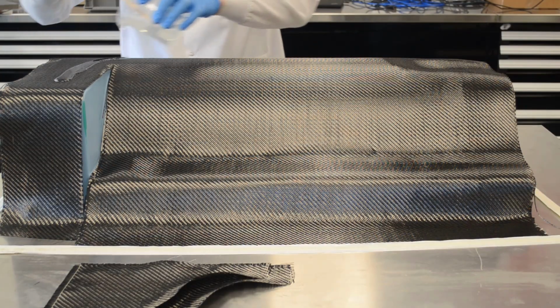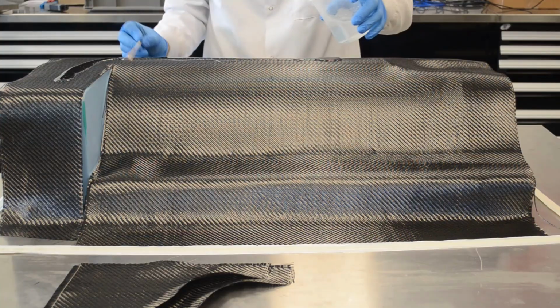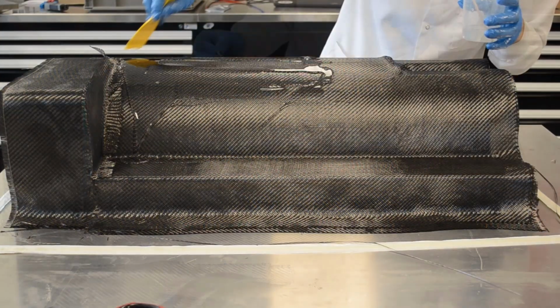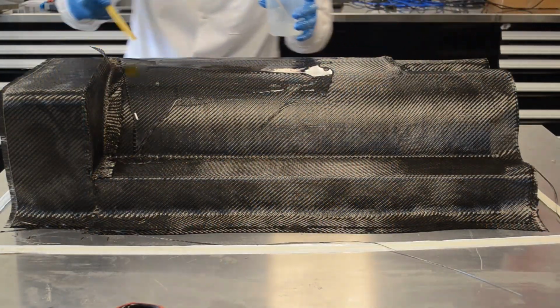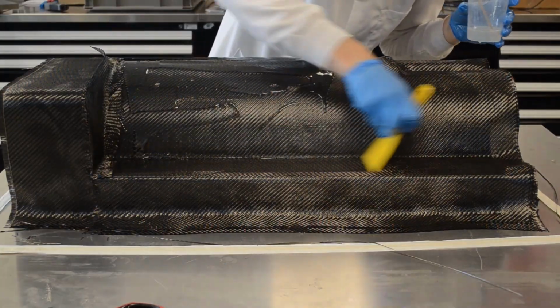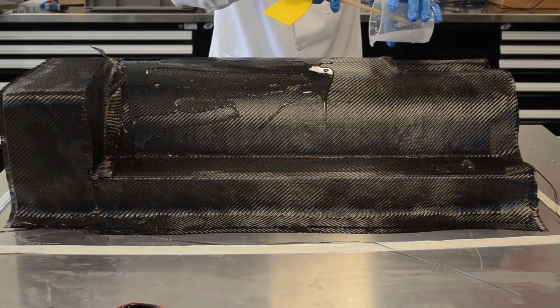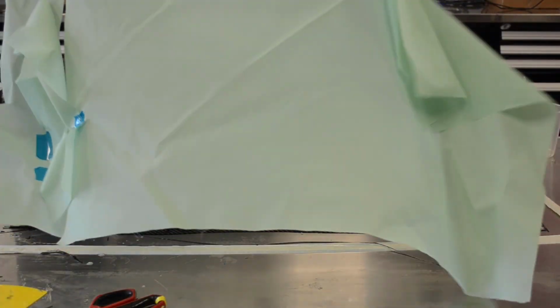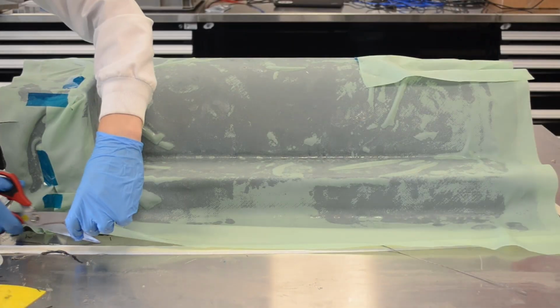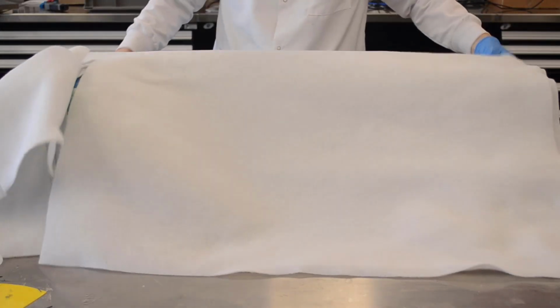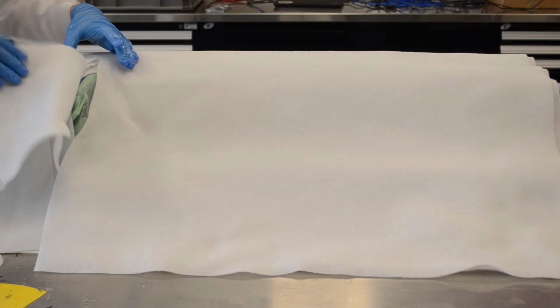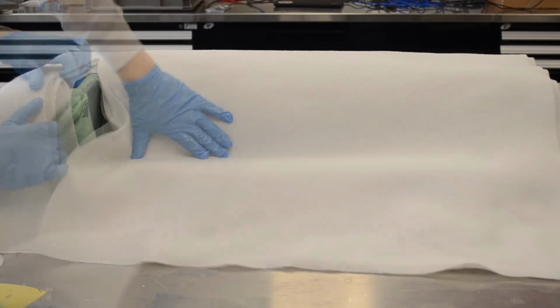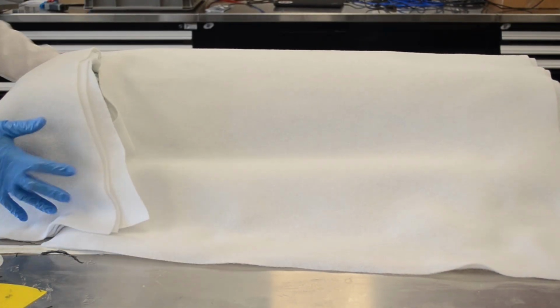For the second part, we will use a vacuum bag. The fiber deposition and resin saturation is similar to the previous part, but it is slightly less critical that resin is distributed evenly, as excess resin is removed via the vacuum consumables. For this test part, we will use peel ply and 3 layers of breather cloth to ensure that all excess resin can be removed. If insufficient layers are used, the resin can soak all the way through the breather cloth,